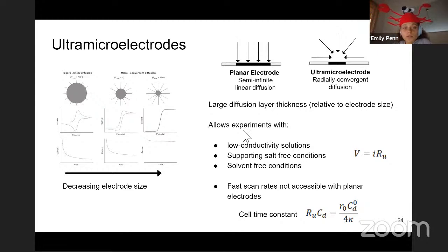A couple of cases where you would want to use ultramicroelectrodes is first, in cases where you might have low ionic conductivity, you might have no supporting salt, or you might not have a solvent. And this is because ultramicroelectrodes allow you to have a really low IR drop. Since the current we're measuring at an ultramicroelectrode is really small, the size of these electrodes is on the order of microns. So we get a very small current. This allows the ohmic drop due to the uncompensated resistance to be quite small.